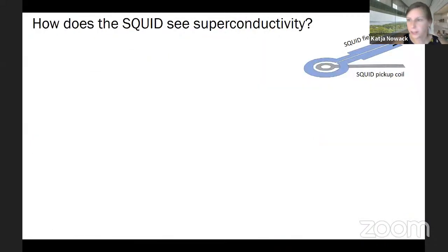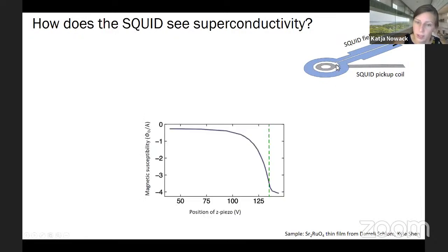All right. Let's talk about how our SQUIDs actually see superconductivity. I told you that we have this pickup loop, and then we also have this field coil. If we run a current through this field coil and measure the resulting flux in the pickup loop, what we essentially measure is the mutual inductance between the field coil and the SQUID pickup loop. And if we do that above a superconductor, if we are really far away from the sample, which is over here, so that's the voltage that we apply to the piezo to move the SQUID in close to and away from the sample, if we do this measurement away from a superconductor, we literally just measure the geometrical mutual inductance between the pickup loop and the field coil.